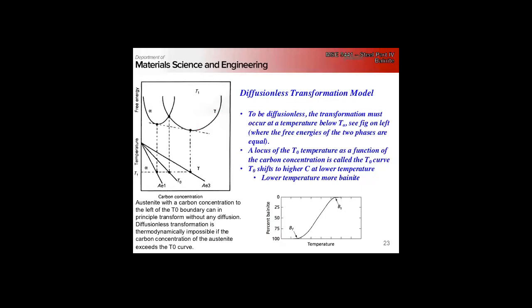It means basically if we're at a composition at a given temperature, we're only going to create bainite. So we make the plate, then we diffuse carbon out. And now the next plate has to nucleate in a carbon-enhanced environment, so it'll nucleate, and it'll still reject more carbon.